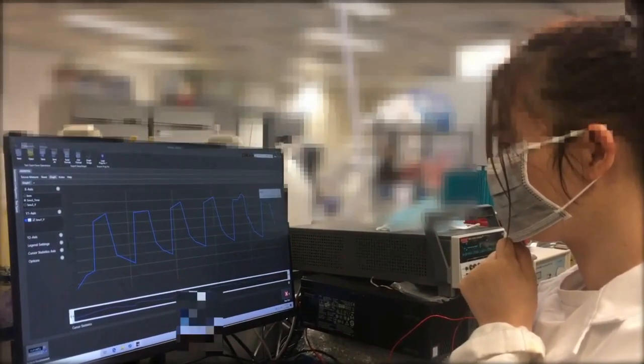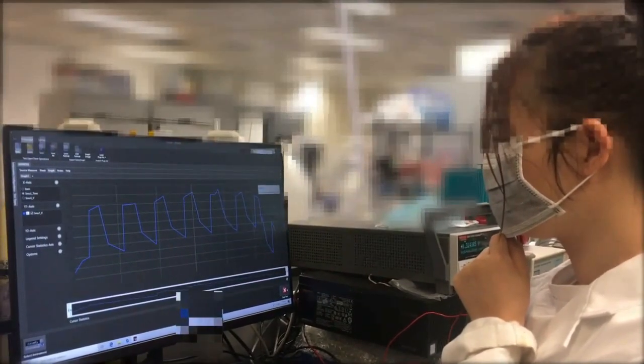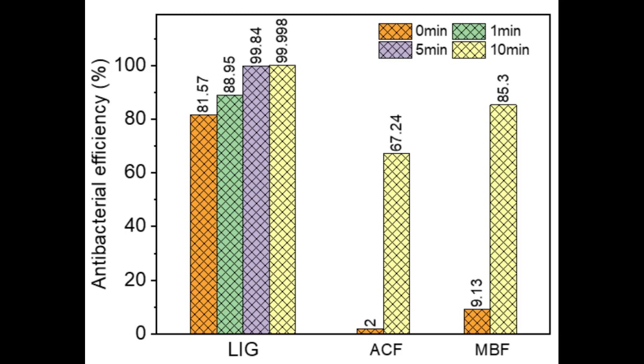can enhance the antibacterial effect. The results showed that the antibacterial efficiency of the graphene material could be improved to 99.998% within 10 minutes under sunlight,